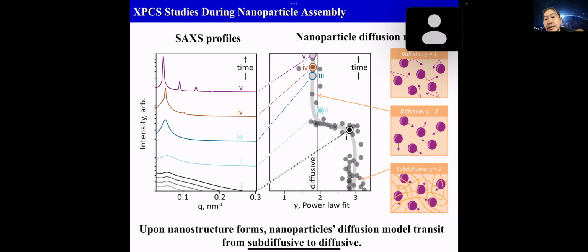In this case, what you see is that in the early stage, the system has this subdiffusive behavior, and this is really consistent with what we showed in the small angle neutron scattering, that the particles are trapped within this polystyrene coil mesh. And then as you start to see a correlation in the system, that means the chains start to connect to form this concentration fluctuation with a certain periodicity, you change from subdiffusive to diffusive. That's where the particles get released from the polystyrene mesh and become concentrated in this P4EP PDP rich regime. And then after that, the system is just going to order.